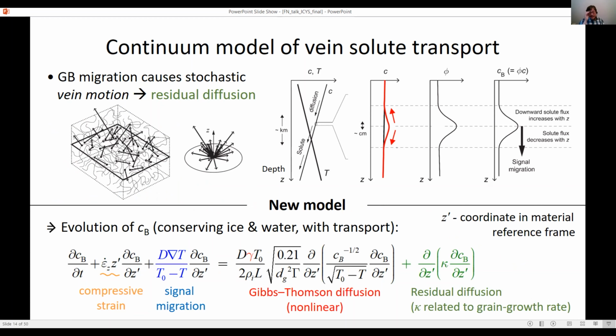As if this is not complicated enough, there's actually another diffusion coming from the fact that in polycrystalline ice, recrystallization is happening all the time. Grain boundaries are moving continually, even if the grain size is constant, and the associated vein motion in 3D in all directions causes an advection. It's like a scattering. It's almost like the kinetic theory of gases. And when you have a gradient in bulk concentration, you get a net diffusion coming from it, at a rate related to grain growth rate.